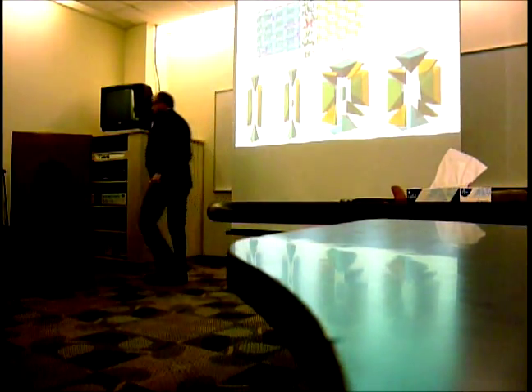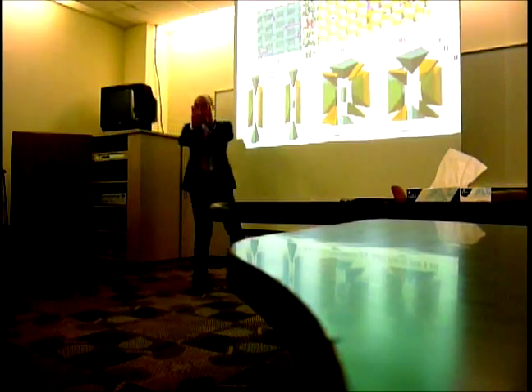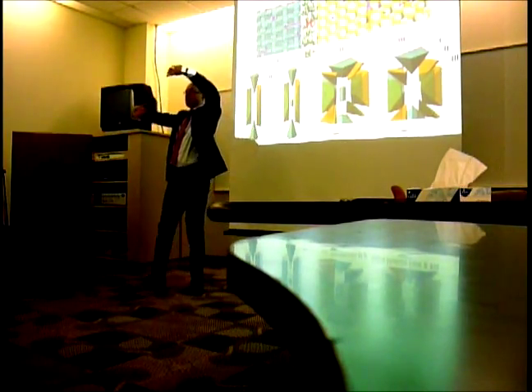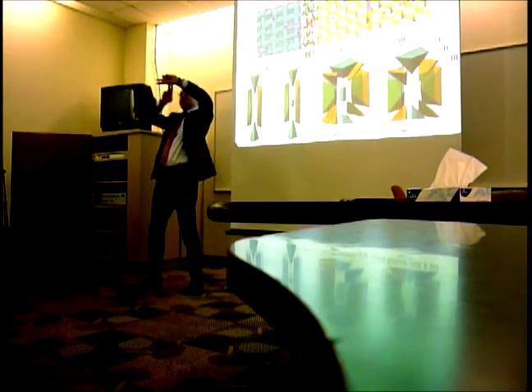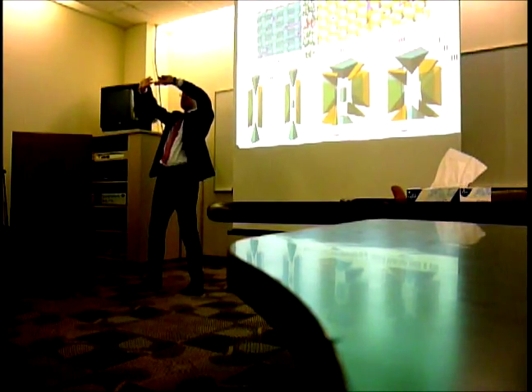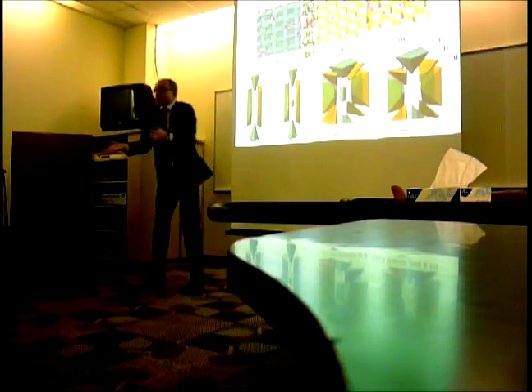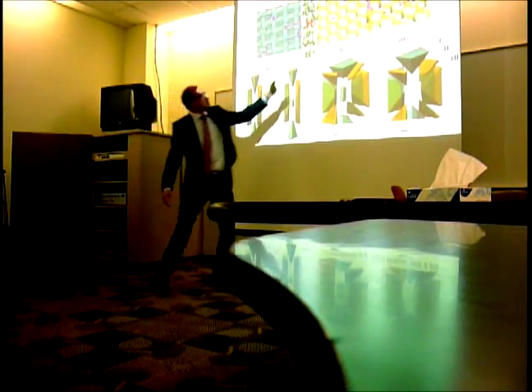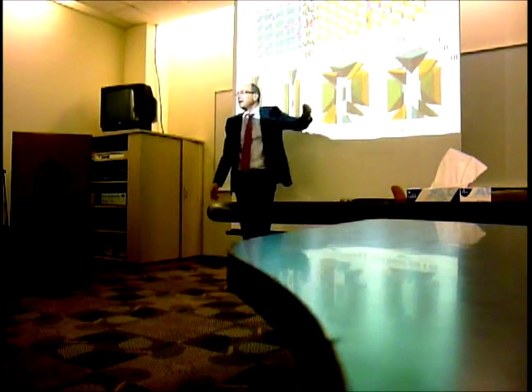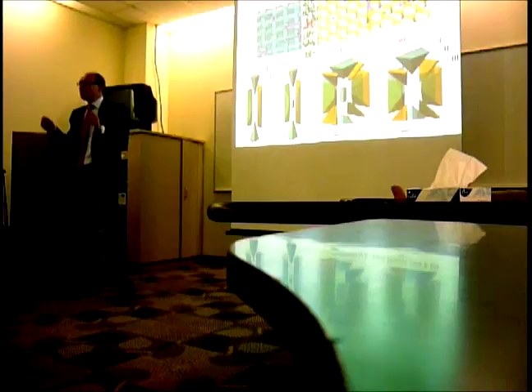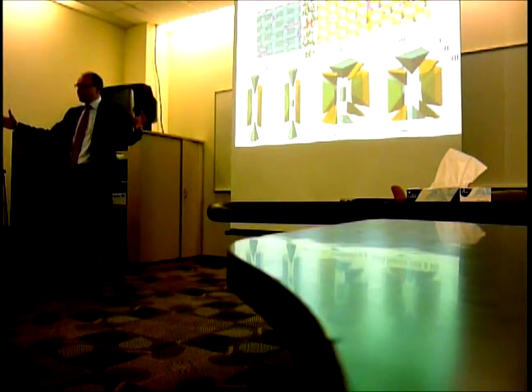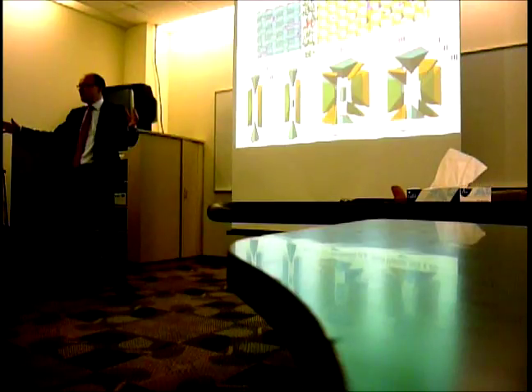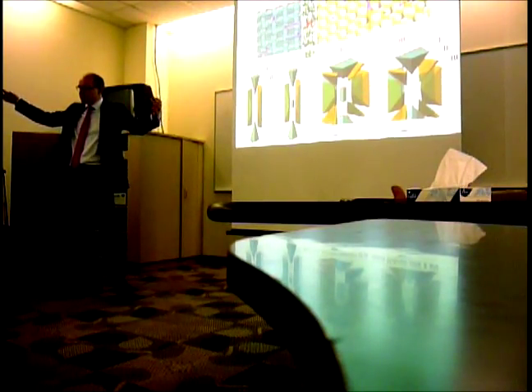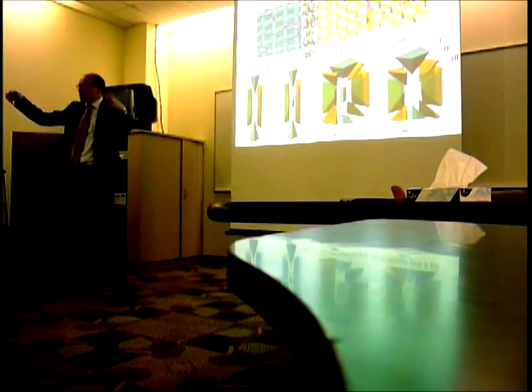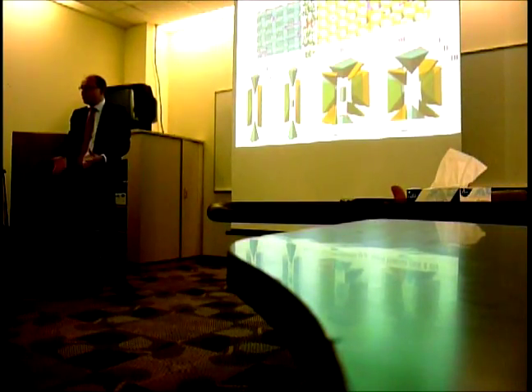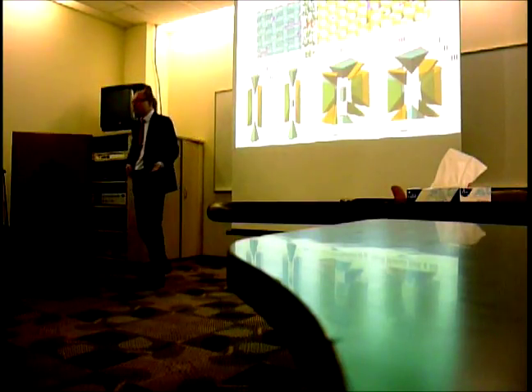And then it even starts to be more complex, because they can be a little bit shifted. So if these are my straight pores, and these are my straight pores, if a molecule comes from here, and it's a little bit shifted, you see what happens? The molecule is stuck. So molecules cannot just travel through the material. In other words, and that's the message I want to give with it, although you have a pretty nice crystal, full of active sites, maybe only the outer surface is doing something, but the inner parts of the crystal will never be seen by the molecule. So it's obsolete for its use then.